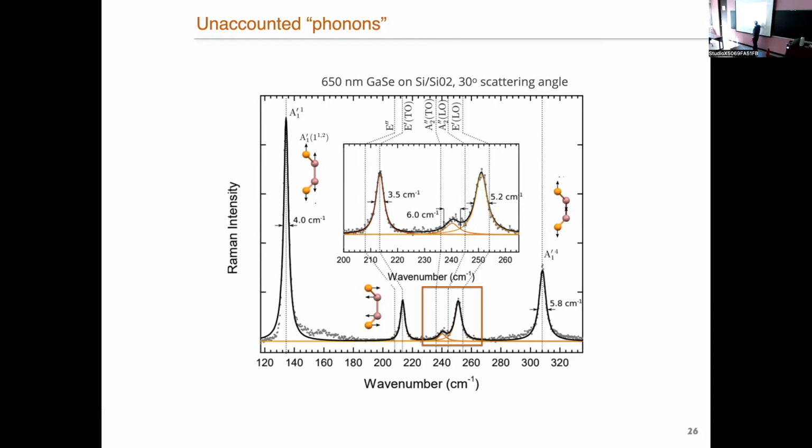This one, this one, this one. But in this particular region, which is zoomed here, we saw phonons that didn't correspond to any frequencies that have been reported before. And even if you would think that it's just a mismatch caused by something, all of the phonons that have these frequencies are forbidden in Raman spectroscopy, so they shouldn't be observed. So definitely, there was something rather interesting.